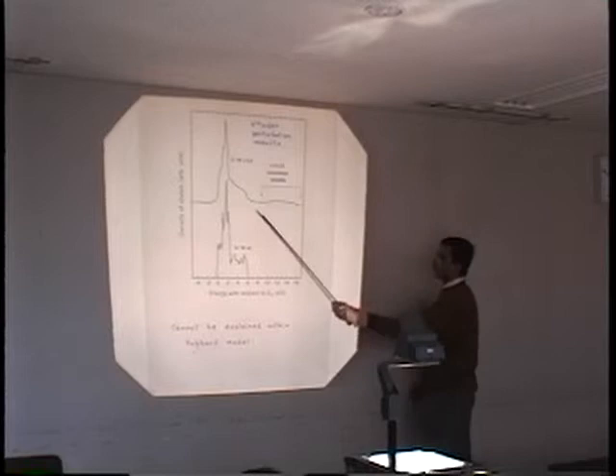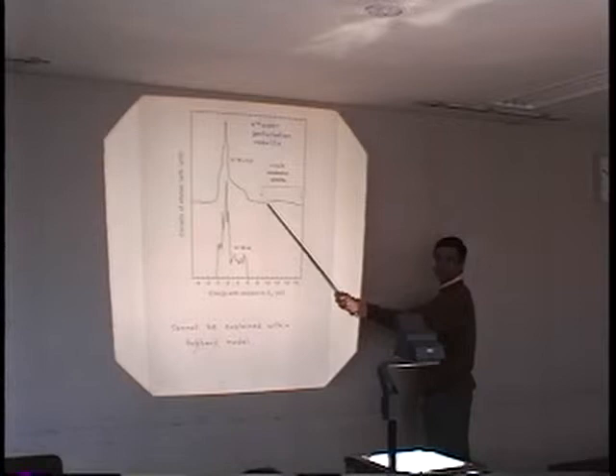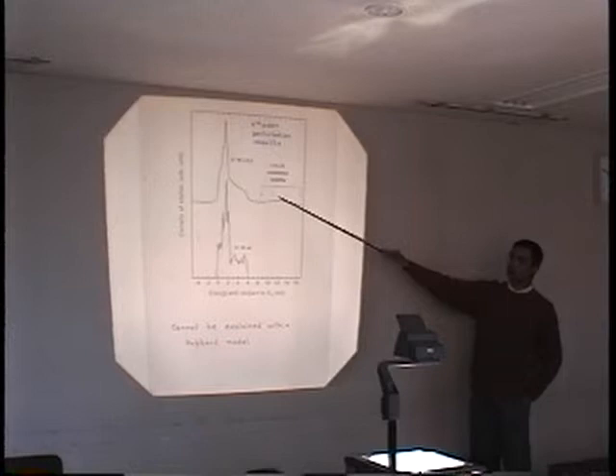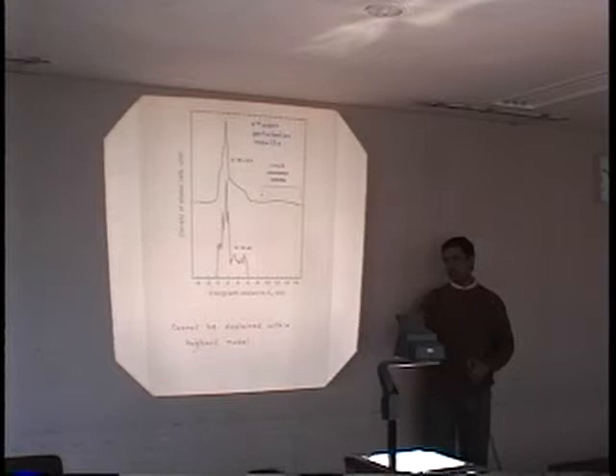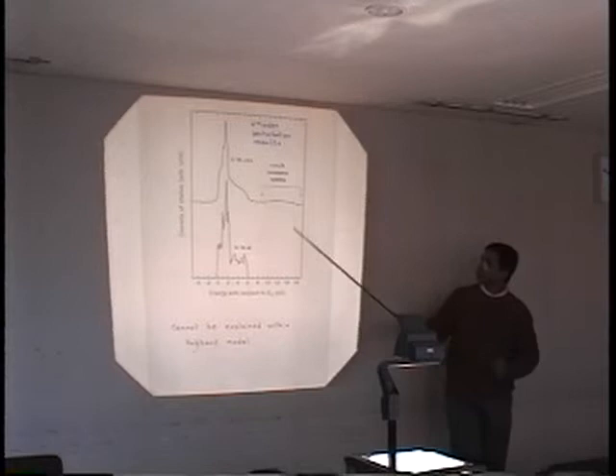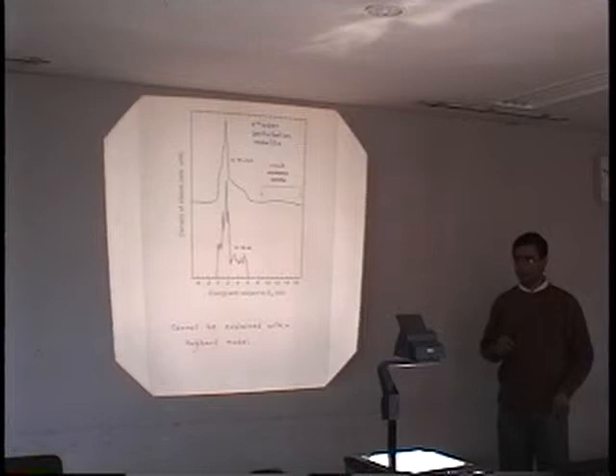a correlation satellite. So if anything, correlation-induced satellite must show up first in the unoccupied part before it does in the occupied part, which is exactly reverse of what we see experimentally. This told us that there's no homogeneous model that can explain such observation.